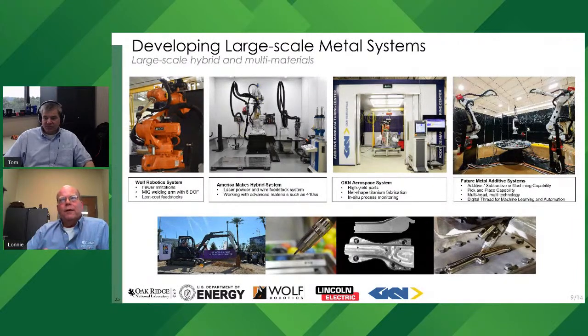We have a partnership with Lincoln Electric on steels, and here it's targeted on making tooling. Right now we're putting down 10 pounds of steel an hour. You'll see the machine on the right called Medusa. It can put down about 40 pounds of steel an hour right now, but we're getting to the point where it's going to exceed about 100 pounds of steel an hour. That machine can make parts that are about 6 feet in diameter, 6 feet tall, putting down 100 pounds of steel an hour. This starts to get exciting. We also are working with GKN on titanium for aerospace, making near net shape, again using a wire as your feedstock and some form of welding, either wire arc, TIG, MIG, or laser to do your welding.